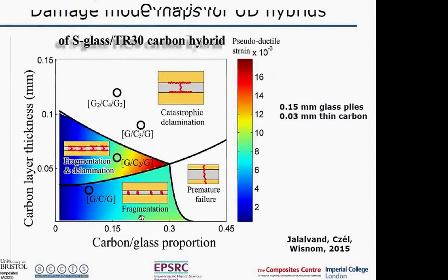We've done a lot of modeling of this, and this damage mode map shows parameters which control it. So there's two main things which control the hybrid behavior. One is the layer, the absolute thickness of the carbon, because that's what controls the delamination. And one is the proportion of glass and carbon. So if we have too much carbon, then we get this catastrophic premature failure of the whole thing when the carbon breaks. On the other hand, if the carbon is too thick, then we get this delamination mechanism.